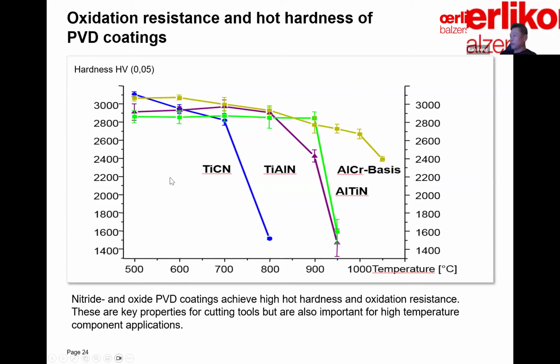For some reason, the DLC coatings are not included in this chart, but I can tell you, if you trust my words, the DLC will be on the left side of this chart. Under 350 degrees Celsius, it will work well, but beyond that temperature, the DLC coating will start to degrade and lose its function. But in practical tribological applications, most of them are under 300 degrees Celsius, so the DLC coatings will work fine.